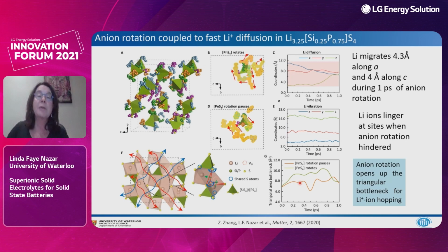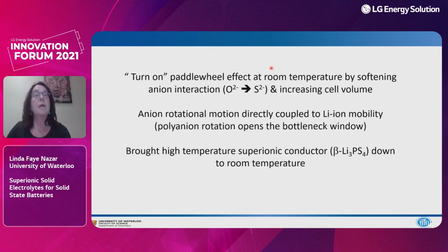So when the rotation pauses, we have about an 8 angstrom window, and when it rotates, we have about a 10 angstrom window. So the short take-home message is that anion rotation opens up this triangular bottleneck, and that is key to decreasing the activation energy. And it does so by about 30%. It depends on the exact material. So my little mini summary is hopefully that I've shown you that we can turn on the paddle wheel effect at room temperature by softening an anion interaction.